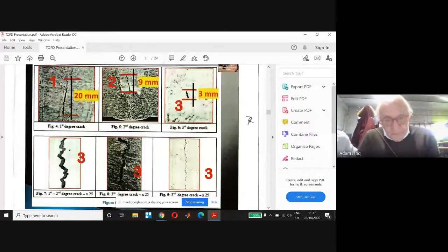But then you have very small cracks. At the right, you see hydrogen cracks or hot cracks. They are not bigger than 3 millimeter. So for this one, it's quite difficult to detect, and you must use a very accurate technique in order to detect this small crack. Next one.